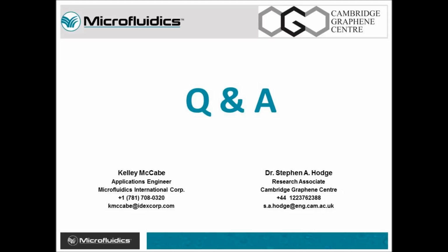That's great. Also, have you attempted to tune your system to over-process your graphene into graphene quantum dots? Very good question, actually, because there is another paper from a group in Israel on the microfluidic processing of graphene quantum dots, so you might want to look at that paper. Yeah, we do have some proportion which is very, very small, so less than 50 to 30 nanometers. If we were to centrifuge our materials at very, very high speed, there's always some fraction which is not sedimenting, and those are behaving like quantum dot materials.